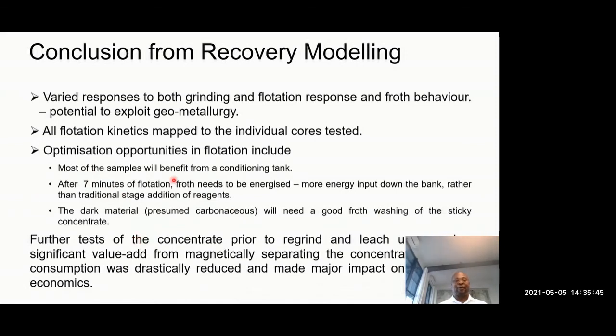Okay. And then something bigger, which I'm not going to spend a lot of time on today: when we saw this, we stepped back and said, actually, what can we do with this entire circuit, from what we have studied in this testing? Because the circuit was going to be done like a normal crush, grind, float, leach, concentrate, regrind, and leach. But when you tested what you do after you've got your flotation concentrate, you realized there was quite a lot of magnetic material in there. And thankfully, a lot of that magnetic material didn't contain much gold.